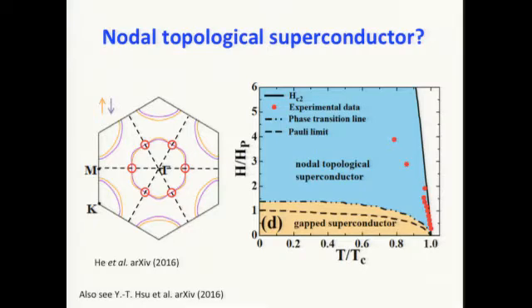But there is actually one interesting observation recently. For niobium selenide, when you decrease the layer number, the TC drops. But for tantalum sulfide, the TC goes from 0.5 Kelvin in the bulk to several Kelvin in a 2-3 layer material. So there must be something changing in that material. So maybe this electron-phonon coupling is changing with decreasing layer number.